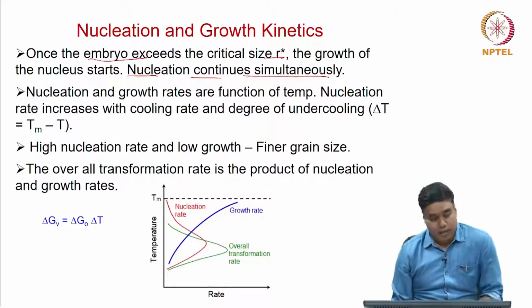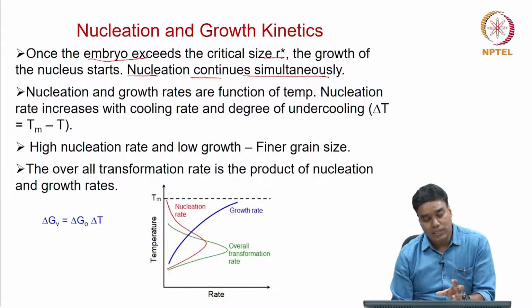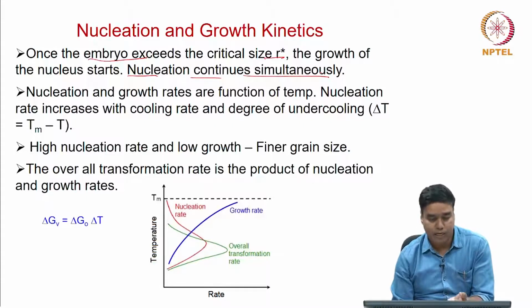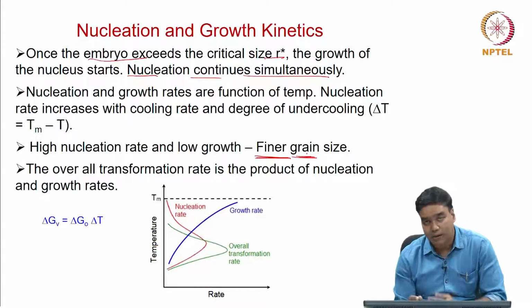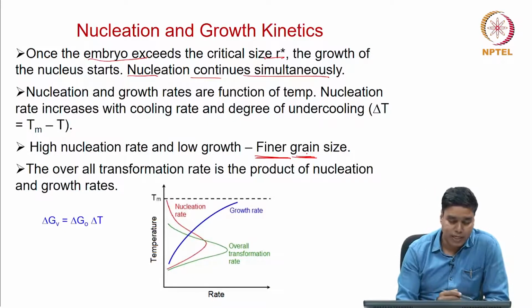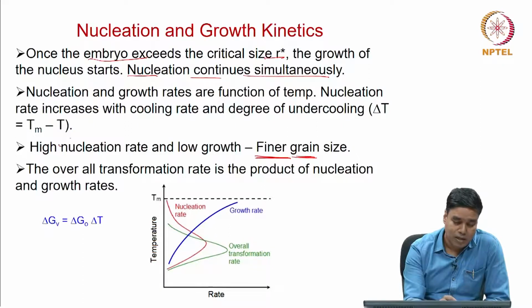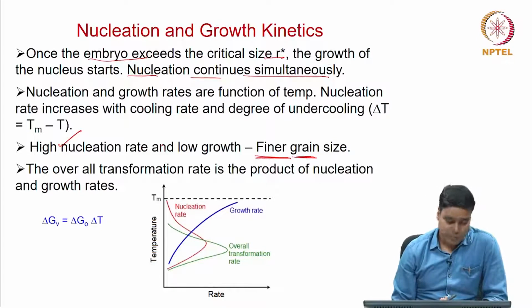Okay. Now, depending on what is the rate of nucleation and what is the rate of growth, your microstructure will be decided. So, whether you would get a finer grain size, that means a finer microstructure or not, is going to be decided by the nucleation and the growth rate, or the competition between this nucleation and growth rate. Okay.